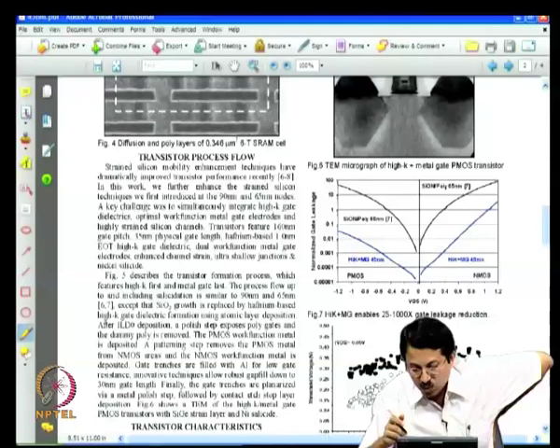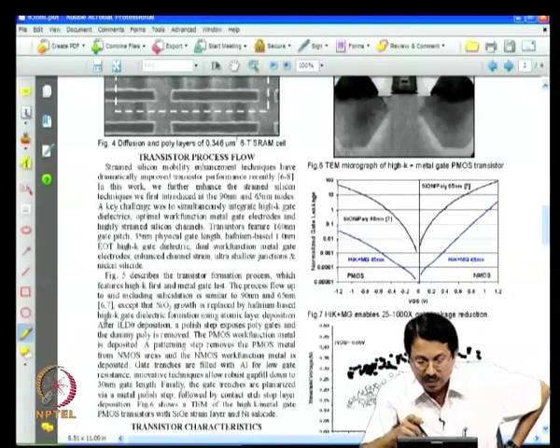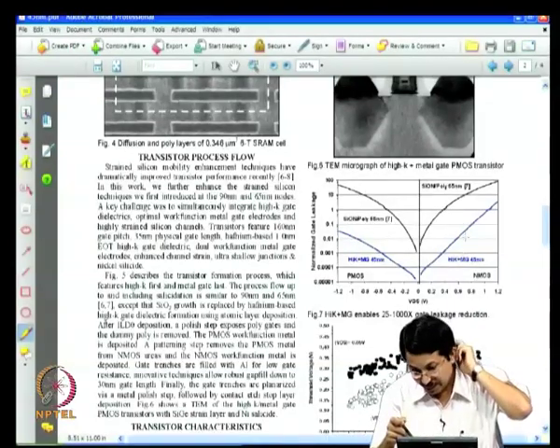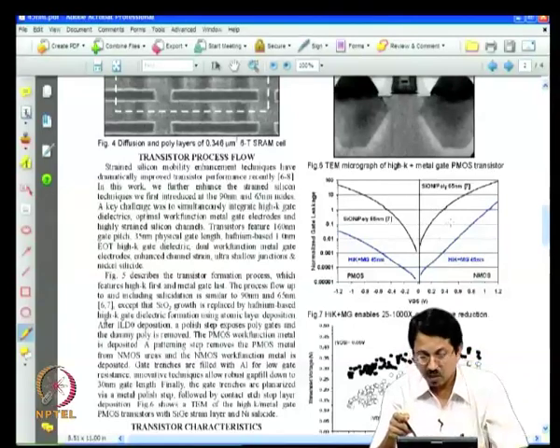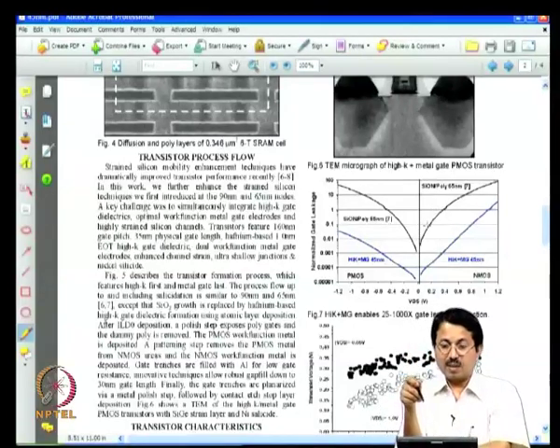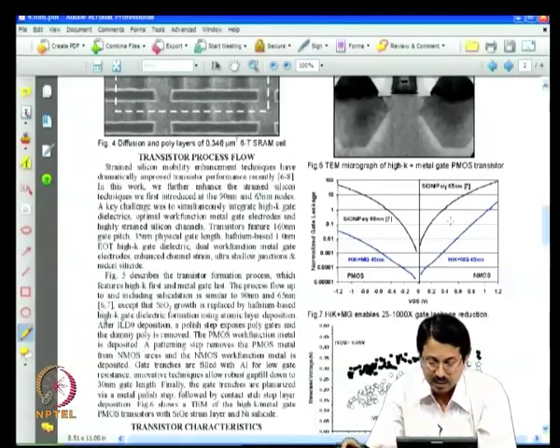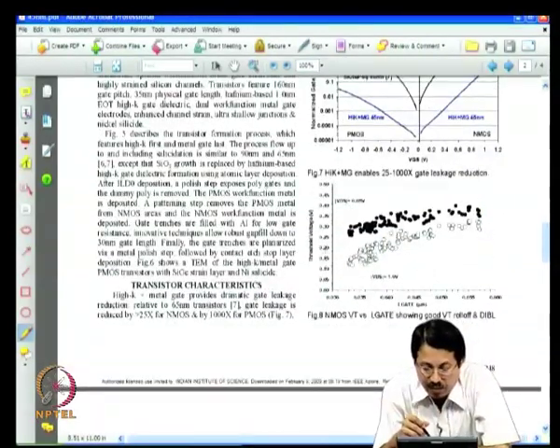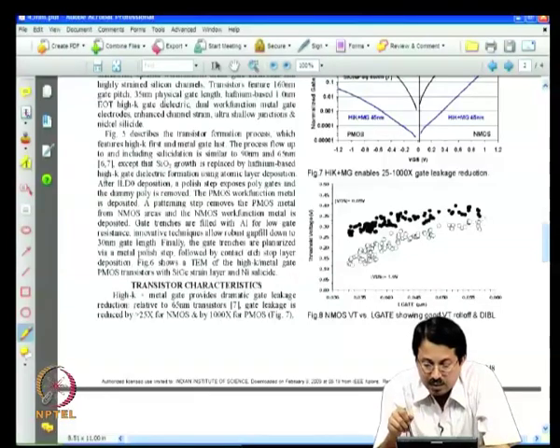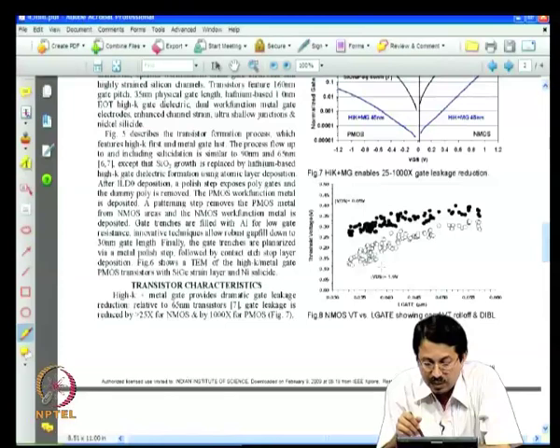So this is again to show that with high K your gate leakage has come down very dramatically. If you had used silicon oxide or even so-called nitrided silicon oxide, you would have had a very high leakage current, but now that is not the case. This is the typical VT versus gate length threshold voltage roll off that we have seen, measured at low drain voltage and high drain voltage.